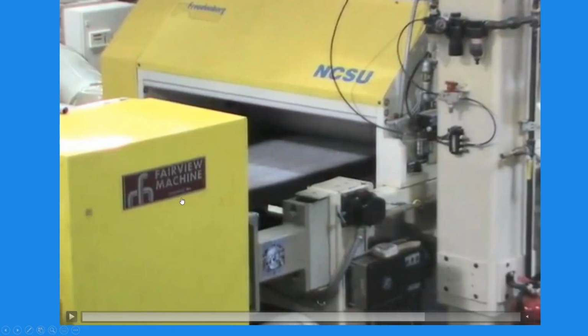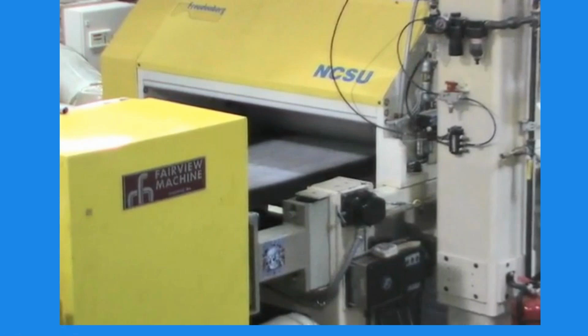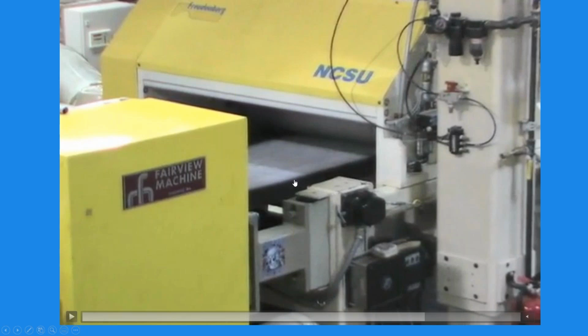Spun bond. Now you can use other bonding techniques. You can use the hydroentangler. You can do things like through-air bonding, where a certain amount of the material is low melt, and you just put hot air on it and melt some of it, which bonds it together. Needle punching isn't generally done; it tears it up because you need short fibers for that. You can do resin bonding as well. So spun bond generally refers to the calender and the spinning. Spun laid usually refers to how we made the web, from spinning up to this point.